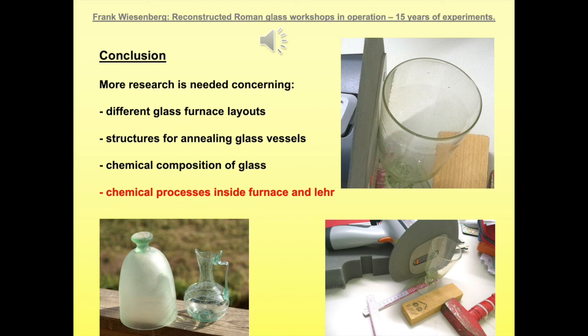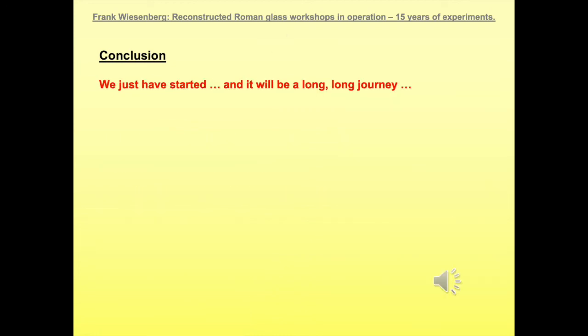And also we had a couple of vessels, such as this sort of Georgian drinking glass, which feature a shiny area of the glass and a dull surface on some parts of the glass. So I did use XRF to examine the composition of the glass, and I noticed that the glass chemistry seems to differ significantly in these two areas of the same glass. So we haven't fully understood all of the effects of Roman glass furnaces yet.